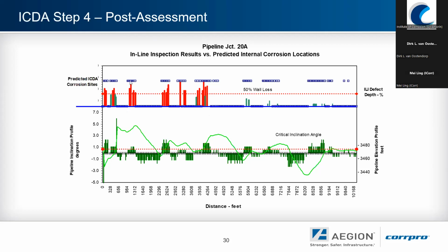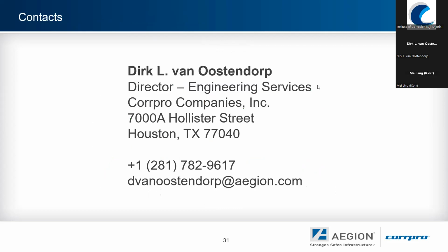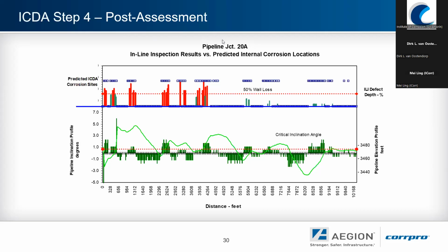So you can see the small bands going across the top. Those were the predicted ICDA corrosion sites, and the red and the green were metal loss anomalies identified by ILI, and the critical depth is 50% at that point. So very good alignment there between the real pipeline data. And I think that brings us up to the end of what I had.